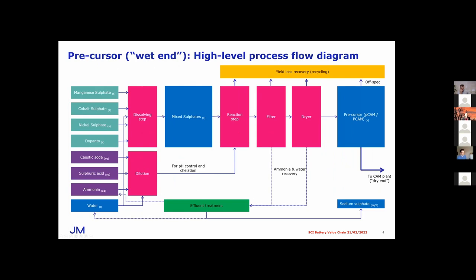So first, looking at the precursor step of the value chain. Here's where we take our various metal sulfates, and we add some dopants to these. The reason you do that is mainly to change the way that the precursor crystal structure appears when you subject it to the reaction phase. You also require some other reagents within that for pH control and chelation, which is actually getting these metals to bond together in the mixed sulfates form. Once you've put all of these materials together in the reaction step, you filter the product, you dry it, and you end up with a mixed metal hydroxide, which is typically called your precursor or pCAM of some description.